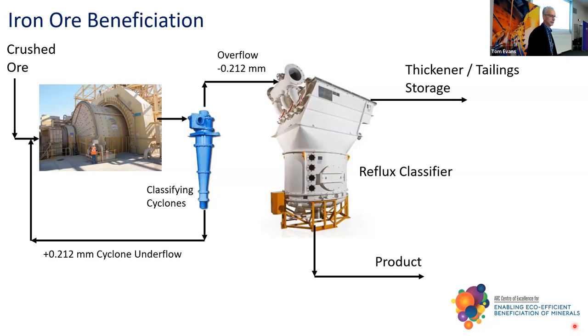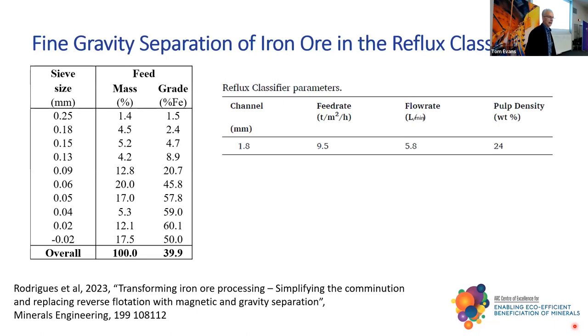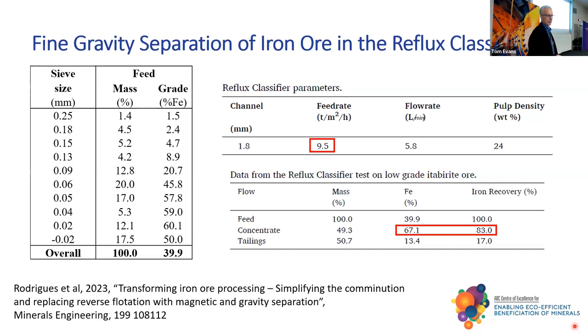This was the feed, and there's a good bit of material below 20 microns. You can see that to get good recovery, you do need to get beyond the 20 micron mark. We were using very closely spaced channels — 1.8 millimetres — which sounds crazy, but I believe there may even be a unit on site right now with those channel spacings. Nearly 10 tons per square meter per hour. One of the very early results was 67% grade, and this has been published just recently.